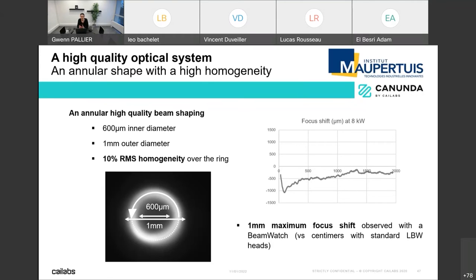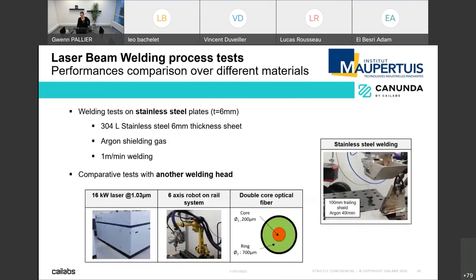And one stop on the image on the right, this is something really unique, but we don't have time to discuss it in detail. Focus shift: when you are doing whatever process using a multi-kilowatt laser, of course, all the objects are heating up. What it means is that the focus plane will actually move quite a lot, it can be centimeters during your process. In our case, because we are using only mirrors, a fully reflective system, we have removed the focus shift. So we have made it smaller than 1 millimeter, which is extremely small, and the process is much more robust.